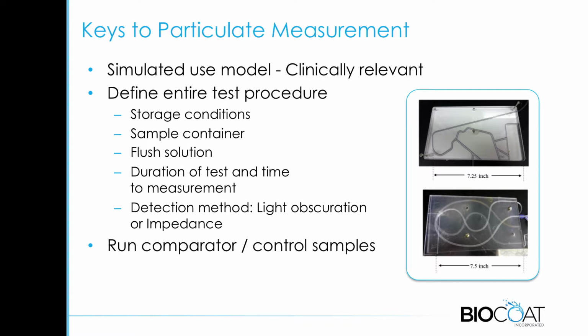The other piece of this is you need to define the entire test procedure, because there are a lot of ways that you can change the values. For example, defining the storage conditions for your device and the solutions. The sample container: is that plastic, is it glass, how are you washing it? Flush solutions: how well you're filtering those, is that water, is that PBS? As well as things like the duration between testing for the particles and the time that you're actually measuring the particles. And then the detection method. USP talks about either light obscuration or impedance methods, and either one can work, but you need to define what that is.